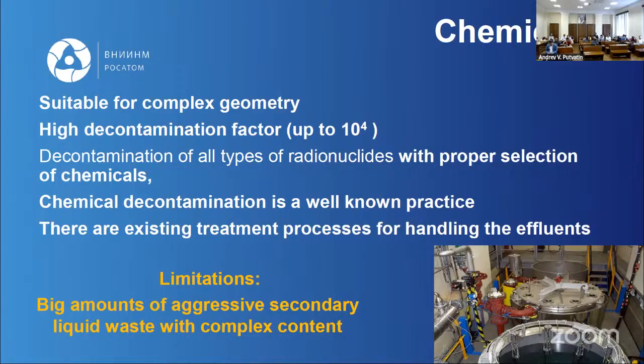But the disadvantage of this method is a relatively big amount of aggressive secondary waste, because for decontamination we apply strong acids or alkali solutions, and for treatment of the solutions after treatment of the surface, we need to apply very strong methods for treatment as radioactive waste, because all this media is very strongly contaminated.